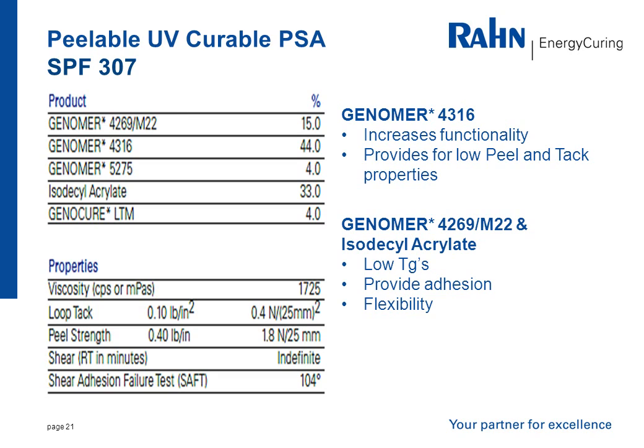We increase the functionality by adding a trifunctional elastomer Genomer 4316, which provides for low peel and tack properties. In combination with Genomer 4269 and diluent isodecyl acrylate, we provide for low Tgs, adhesion, and the flexibility we need for the PSA upon removal. We have just enough loop tack, 0.1 pounds per inch squared, peel strength, 0.4 pounds per inch to have a